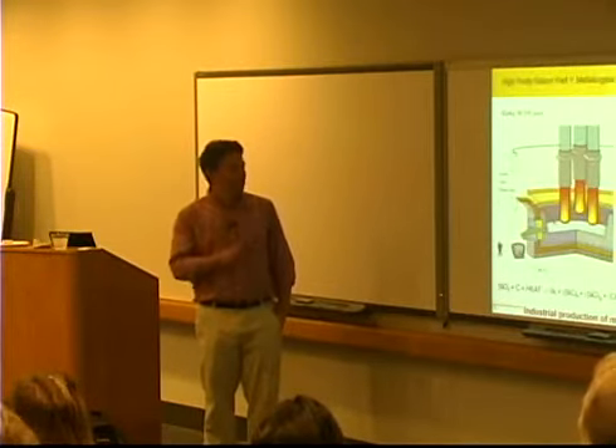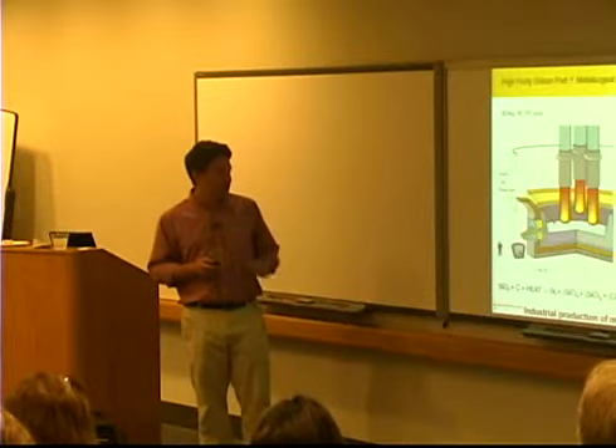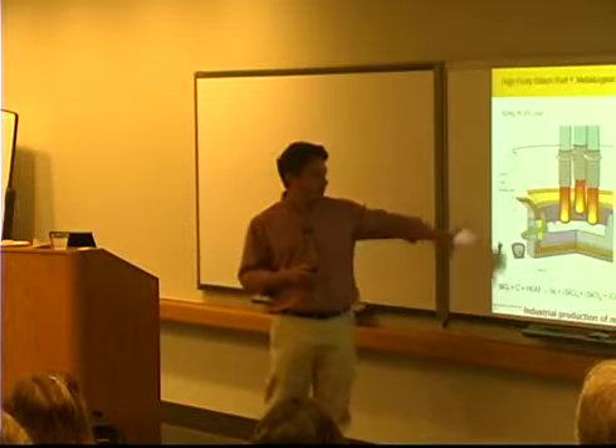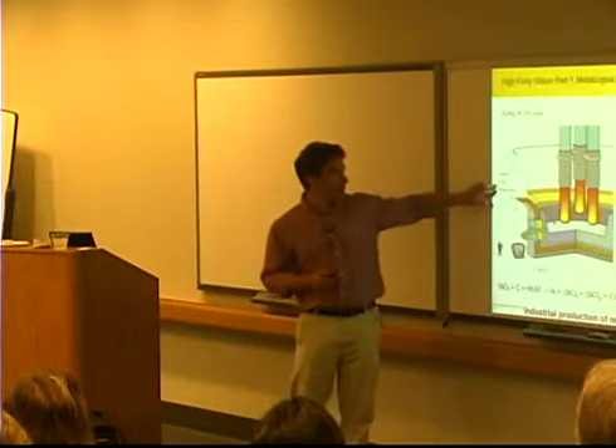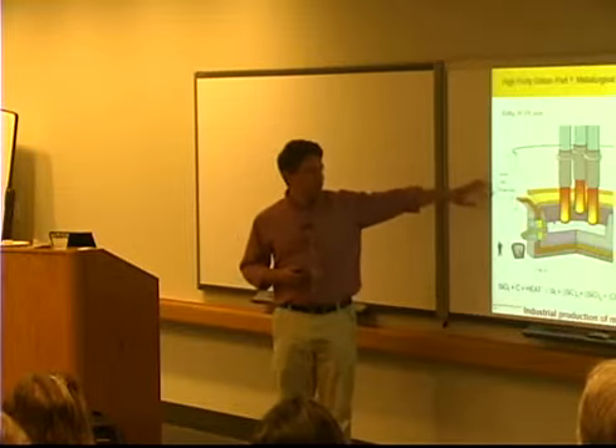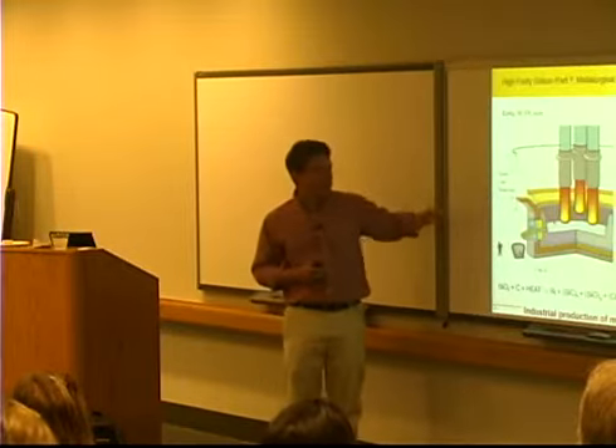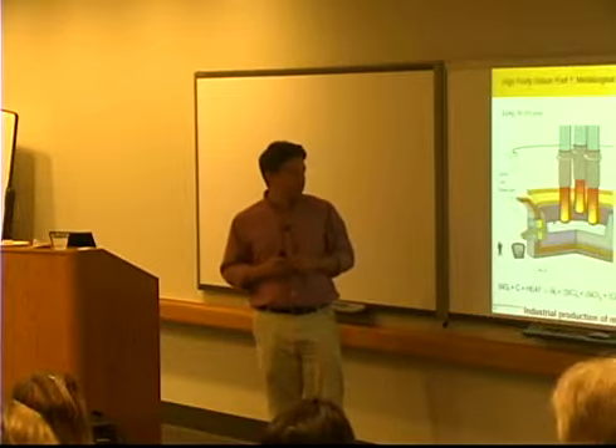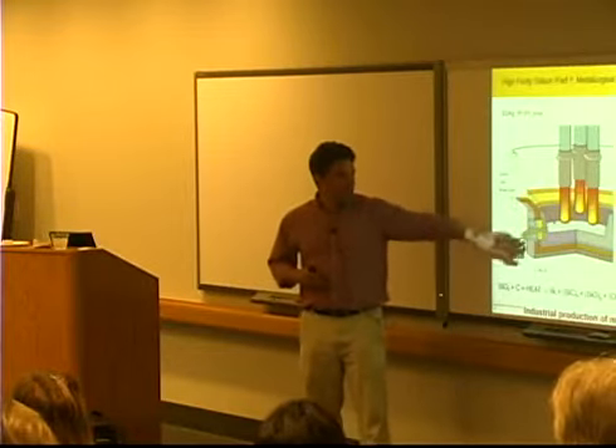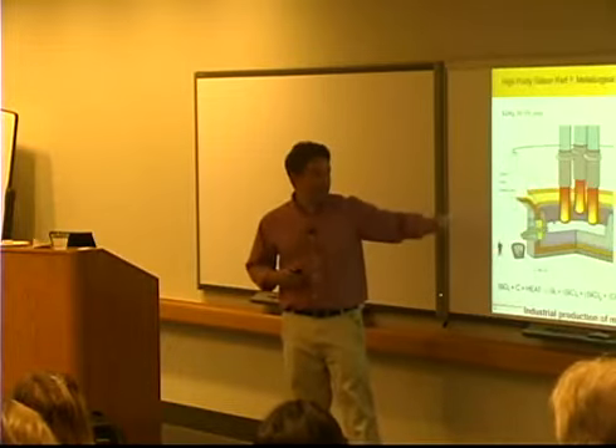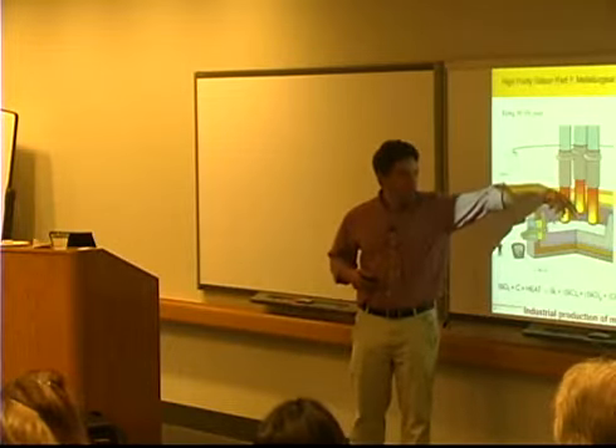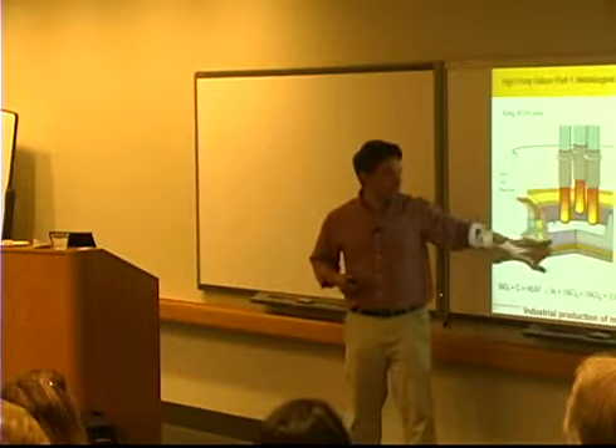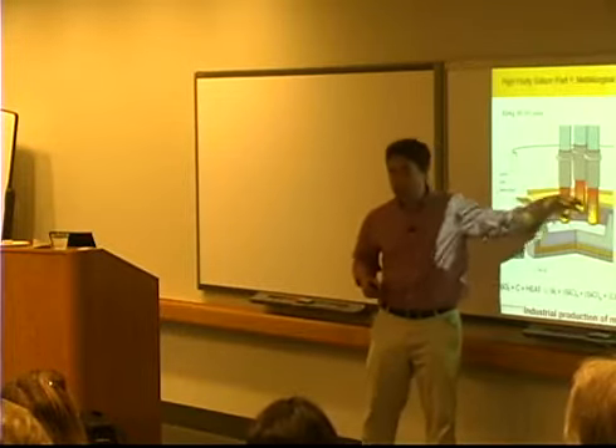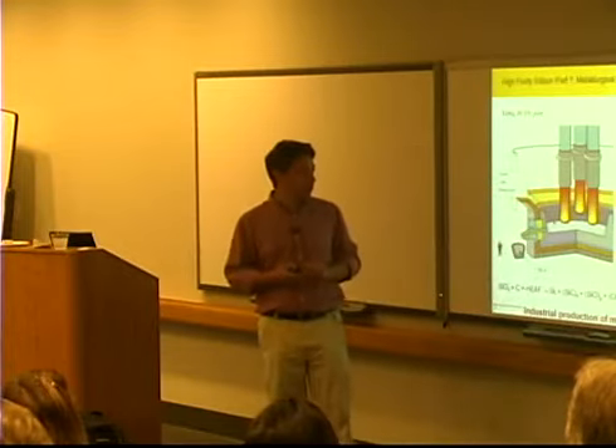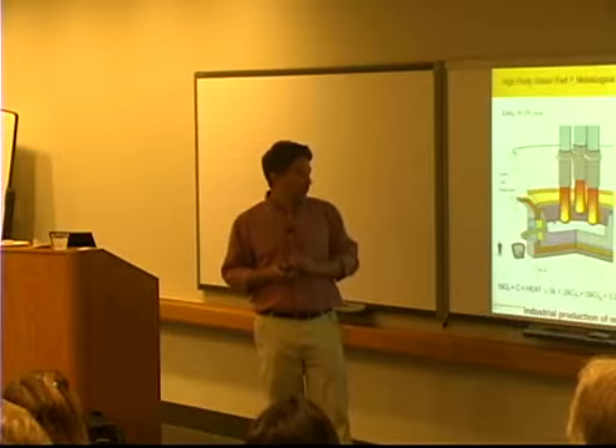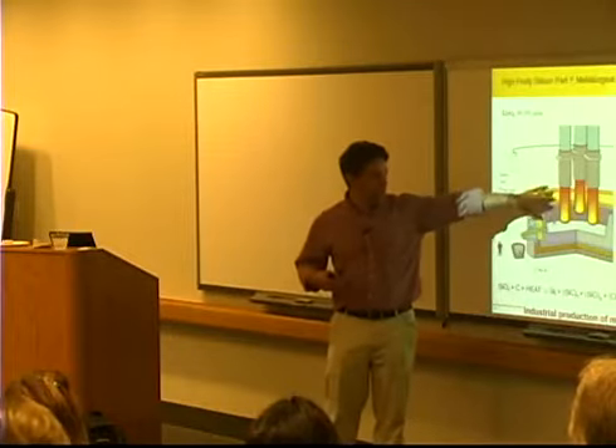In the meantime, how do you make high purity silicon? You start with quartz, coke, and wood chips, and so you have silicon dioxide, and then you have carbon sources to reduce the silicon dioxide down to silicon. They have these gigantic furnaces that do this, and they come down with 3 graphite electrodes here, and typically this big bed here would be filled with these raw materials that come in on rail cars and then are brought in on big trucks and just dumped in here.